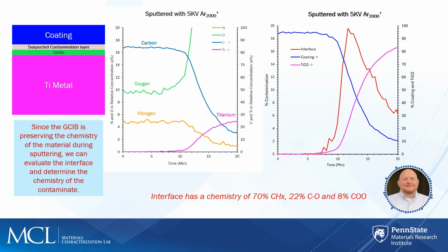But here with the GCIB source, we can very quickly model what the organic is of the coating, create that model, and then subtract that from what's left over, and we'll see this interface region. And it turns out the interface region ends up having a high level of aliphatic carbon, CO, and carboxylic acid. It's not an unusual organic to see in an interface, but in this case, it allowed for delamination of that coating on the oxide substrate. So it gave us the ability to actually see what was happening here and tell somebody about the material that we have not had the ability to do before now.